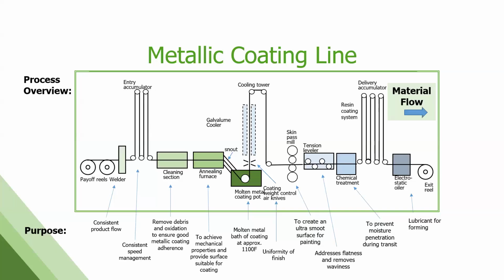It comes out of the furnace through the snout into the molten metal pot. So this is a giant pot that's got zinc and aluminum ingots that have been melted into it in the right ratio for that coating to stick to the steel. So the steel strip moves through that bath and comes up out through the surface. We have a set of air knives there. Those air knives, high-speed jet air that's being impinged on the surface, control how much of this metallic coating weight we put on there. We'll talk a little bit later about coating thickness and weights and why you measure that.